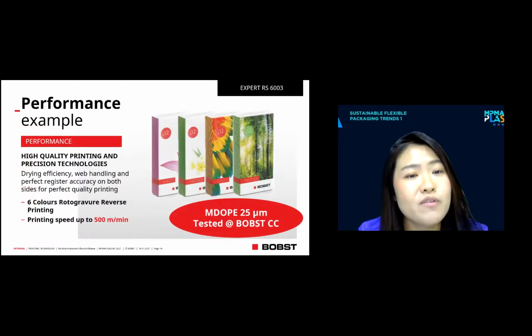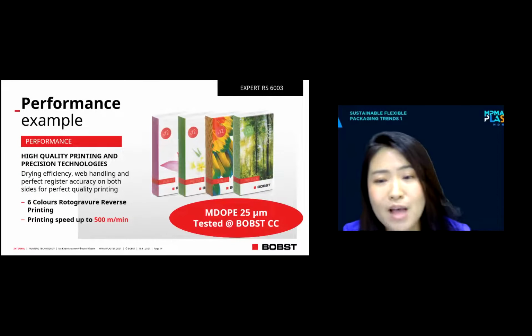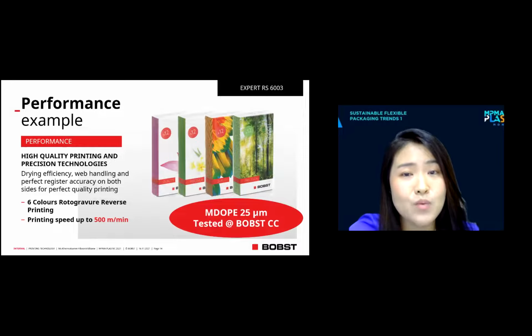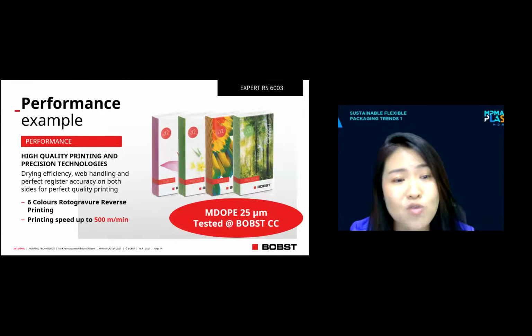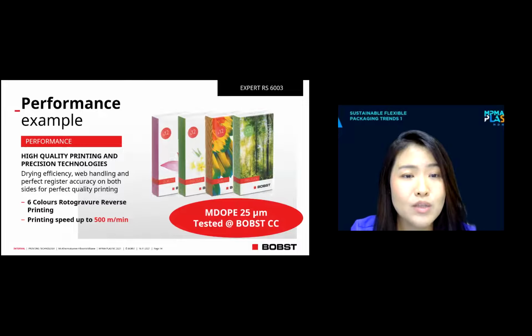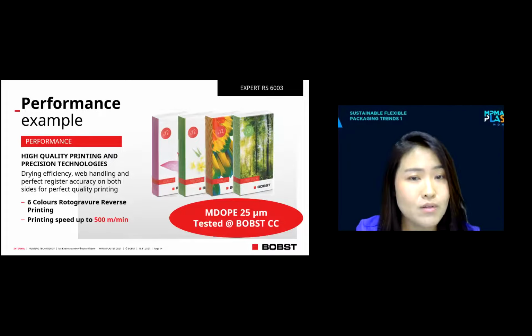So this is our performance sample. We're talking about our rotogravure, where we use MDOPE 25 micron to print at a maximum speed of 500 meters per minute. On the rotogravure this is also quite critical, but our dryer and our registration control also help us to improve this. And this is not only a concept model. Our customers nowadays can already print MDOPE film on our rotogravure.